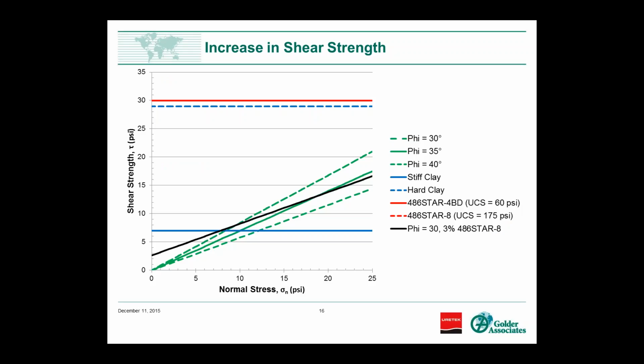So now what I did then is assume a simple volume replacement. Assuming there's some pore space in there that you can fill with this material when you're doing the deep injection, what happens, for example, if I do a 3% volume replacement? For this example, I'm using the 30 degree friction angle soil. That's this bottom dashed green line. And I replace 3% of the volume with the higher strength material. And what I end up with is this black line.